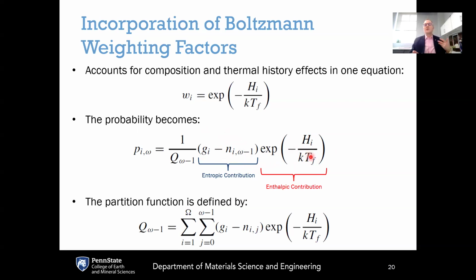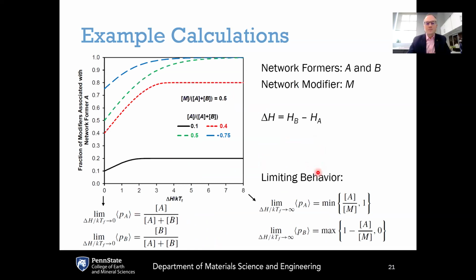And the resulting glass structure that you get can be more entropically favored if it is a higher fictive temperature, or it can be more energetically favored if it is a low fictive temperature. And so this is really the basis of the statistical mechanics that governs that balance between entropy and enthalpy as dictated by the thermal history of the glass represented through its fictive temperature.